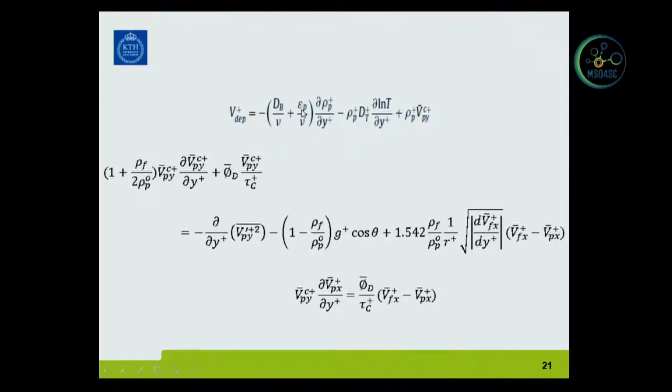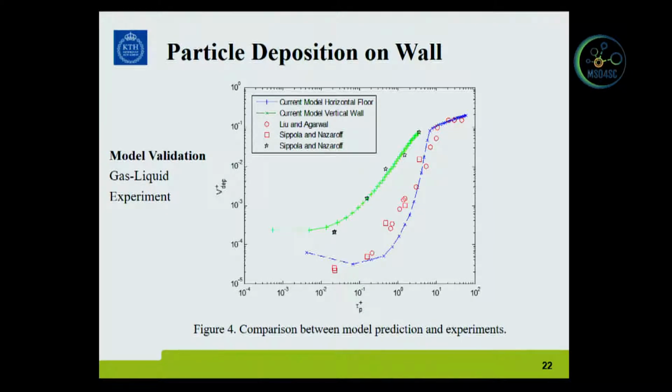One is the added diffusivity. The other is the particle mean square velocity. Here we need an assumption. We assume it is equal to the fluid property, and this property can be found in the literature. Therefore, the only input for the model is the friction velocity, and then we get some inputs from the literature. We don't need to solve the boundary layer again. Then we can know the inclusion transport flux.